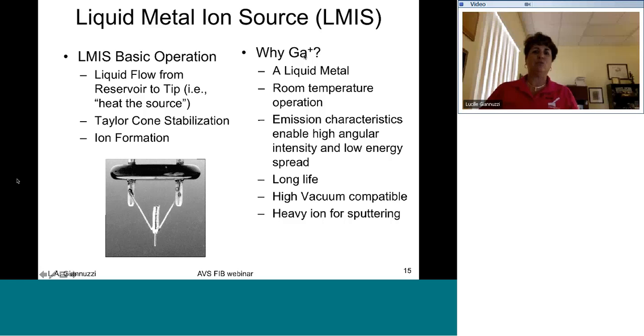So people always ask why gallium, and basically it's because gallium works really well in this type of source. It's nearly liquid at room temperature, so it's really easy to control. As I said, you only have to heat it once and then use it for hours and hours before you have to heat it again. Its emission characteristics are really good. It gives you really high angular intensity and low energy spread, which reduces the aberrations, long life, high vacuum compatibility, and it's a heavy ion for sputtering. So basically it gives you the best of all worlds, and it's easiest to use in a commercial instrument.